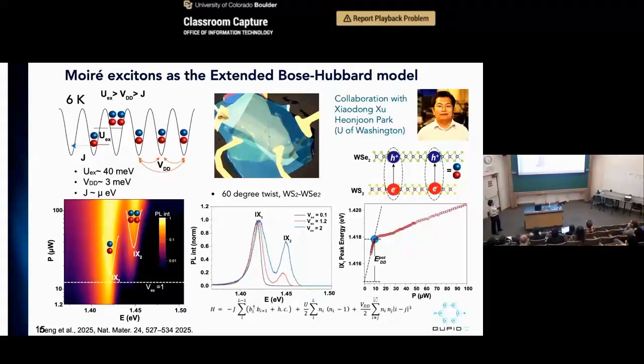First we want to do some spectroscopy to characterize the energy scales in the Bose-Hubbard model. What we did is first a steady-state PL measurement, where we look at the exciton emission as a function of density. At very, very low density, we only see one single emission band, coming from the interlayer state. As we fill the excitons beyond 100%, or a filling factor of 1, we start to see a second, higher-energy emission emerge. This energy difference has to do with forcing two excitons onto the same site, which gives a strong repulsive interaction. This strong repulsion comes from the fact that in the Moiré site you restrict the configuration of the excitons, so you cannot actually form a bound state of a biexciton, for example, because they cannot rotate. So this strong repulsion comes from the strong confinement of the Moiré lattice.